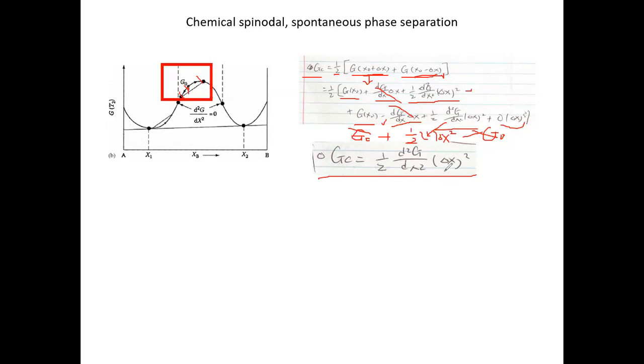Before and after the fluctuation, right? It's clearly proportional to delta x, which is kind of the driving force, but also the key factor, because this is going to always be positive. So whether the free energy difference is going to be positive or negative can only depend on which factor? The second order derivative of the free energy with respect to composition, which is exactly this guy, right?